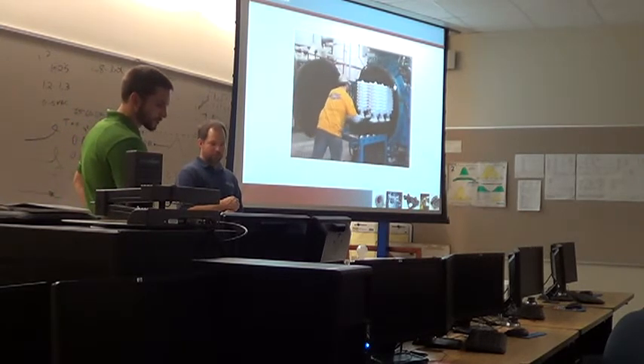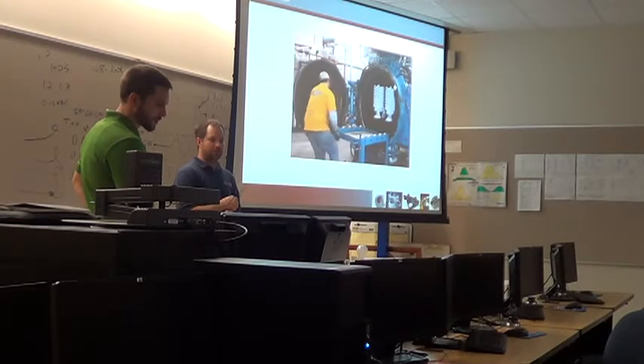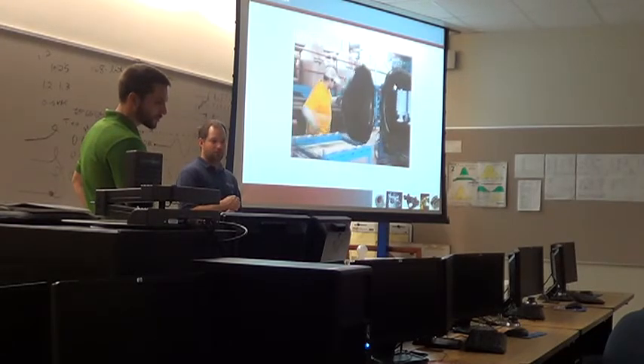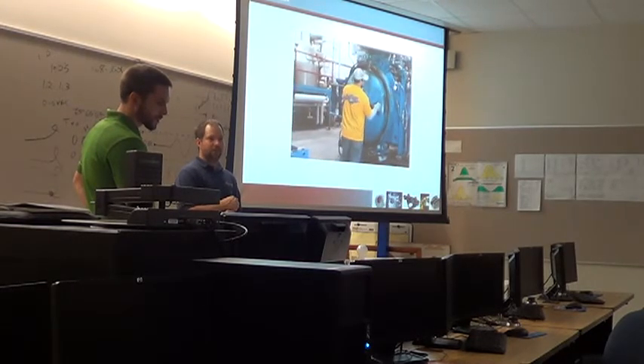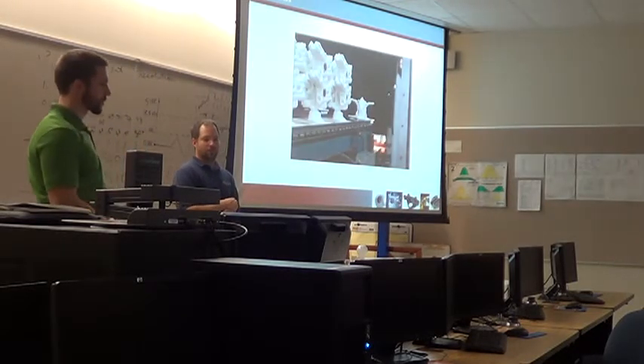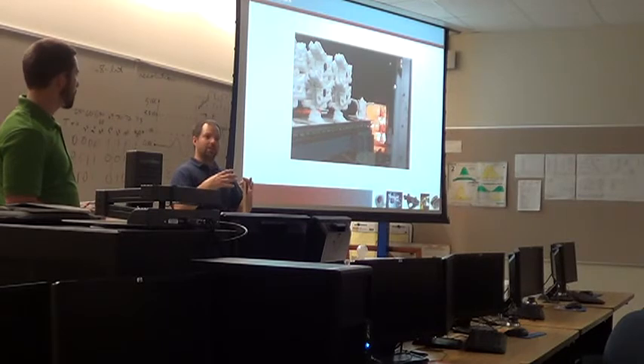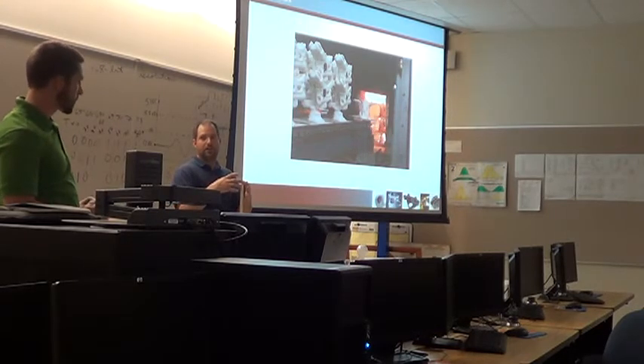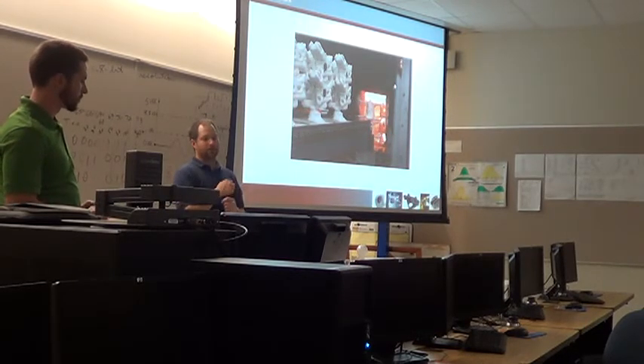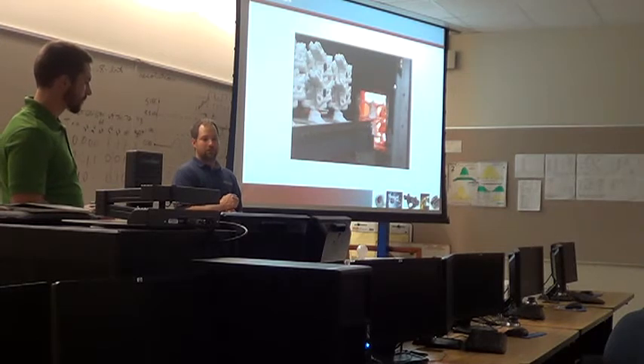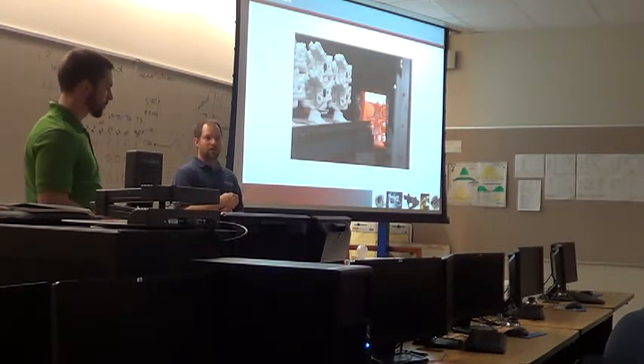So as you can see, we push the cart into the autoclave. He's going to close the door, and as soon as he closes the door, a big steam valve opens, steam rushes in, and that's where we get that high pressure and high temperature almost instantly, like I said, within about 3 seconds. So what that does is hold pressure on the outside of the shell, keep it from cracking, and then the heat melts the wax off the bottom. So after that, we have all of the bulk of the wax out of the mold.